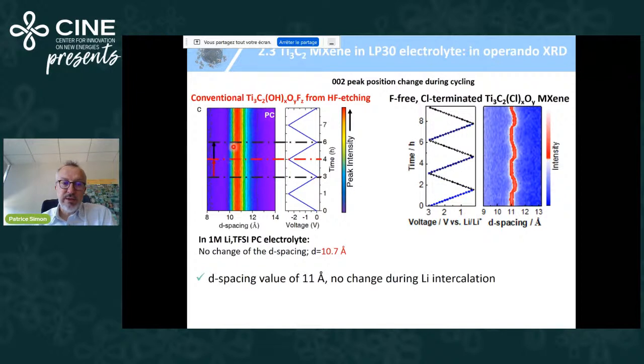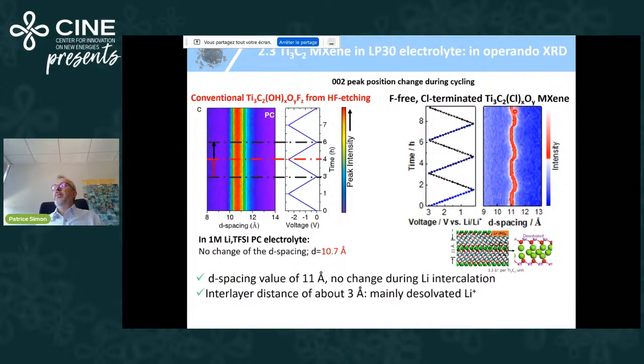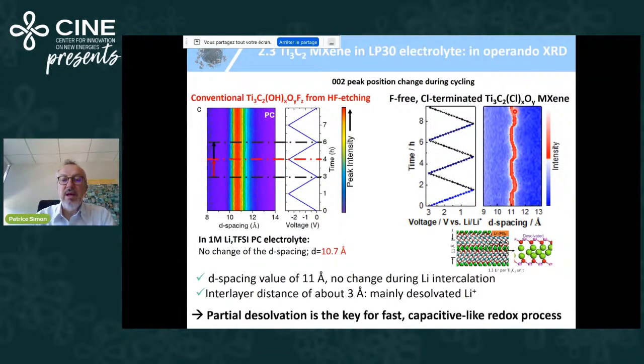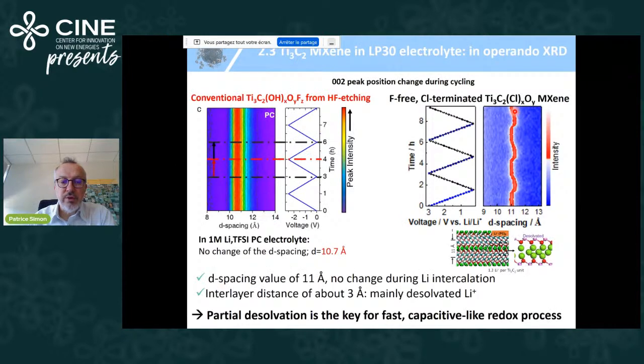And finally, I told you last time, this is more or less the same experiment we did. We tracked the 002 peak position. This is previous results, and this is the new result in LP30 electrolyte. You can see that we have a mean interlayer distance of 11 angstrom, which does not change that much as well. So we can assume that lithium ions are mainly desolvated between the layers. And again, when they are mainly desolvated, you have high capacity and you have capacitive-like redox process. So this is the conclusion.